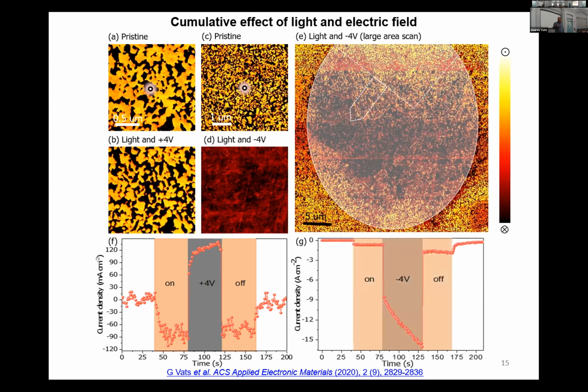With the negative bias, I see some photocurrent on turning the laser on. On applying -4 volts, it goes all the way up here. There is time dependence. And then on turning off, it goes back. And if you look at these units, there is a difference of a few orders. So in this case, light is actually supporting the applied negative bias, and in the other case, it's opposing the positive bias. And using a combination of voltages, we can have any intermediate state here, and we can also play with the light intensity and the laser spot size, which is interesting for applications such as neuromorphic computing or memristive applications. So that's what we did.